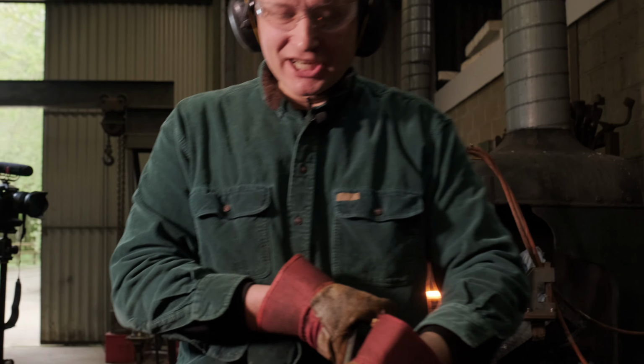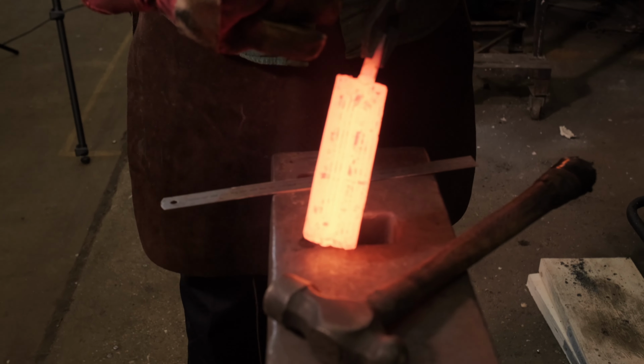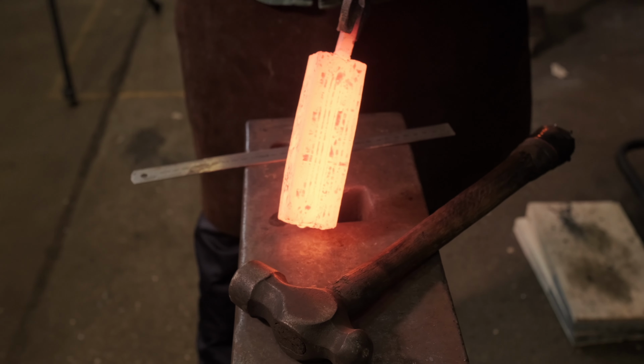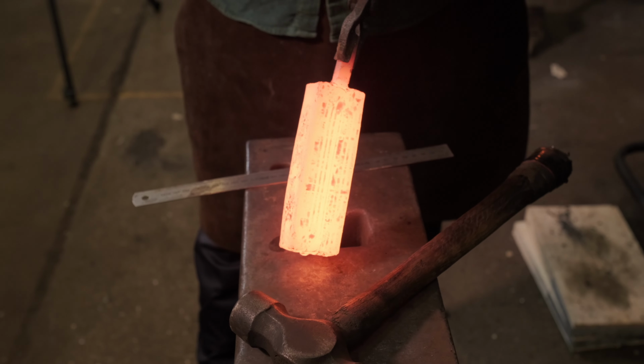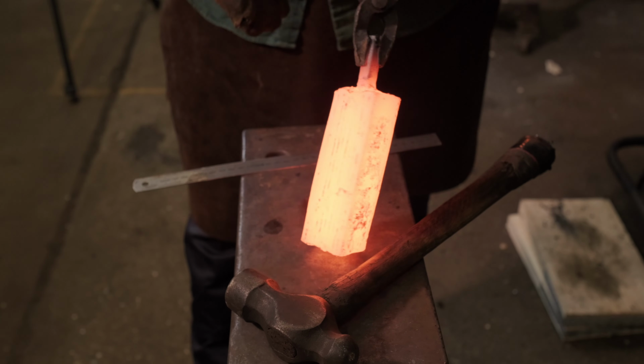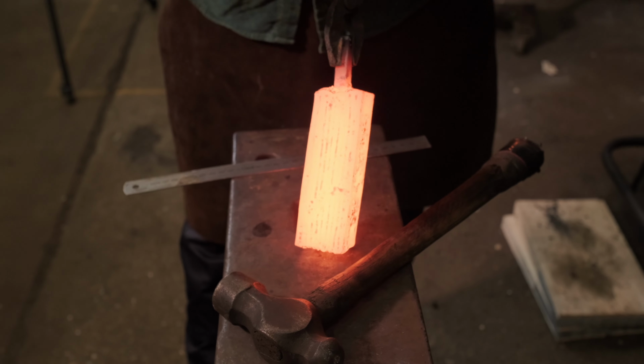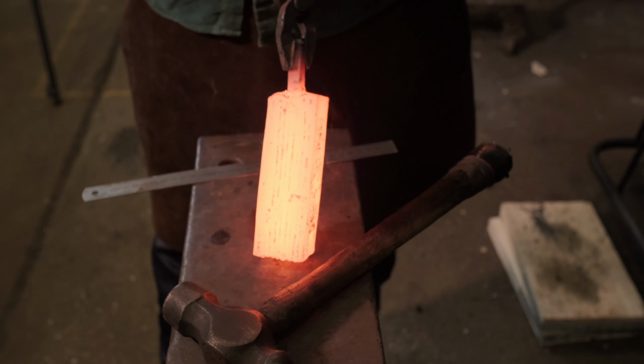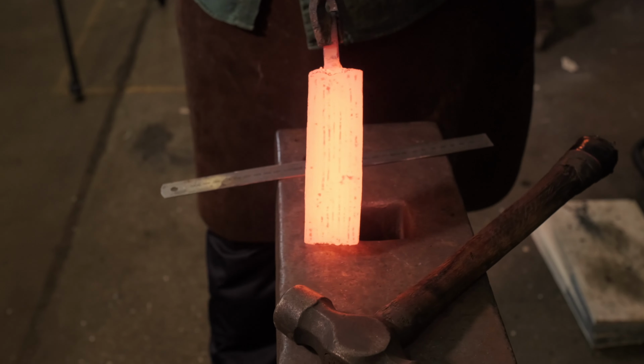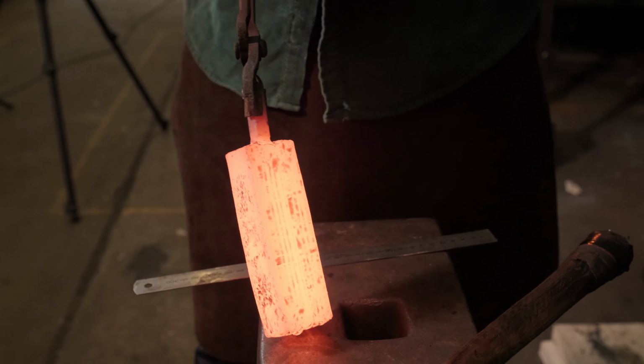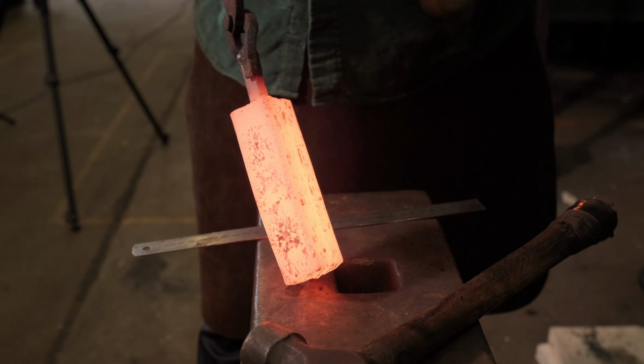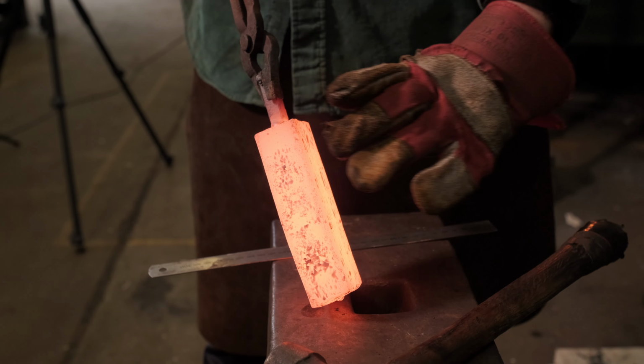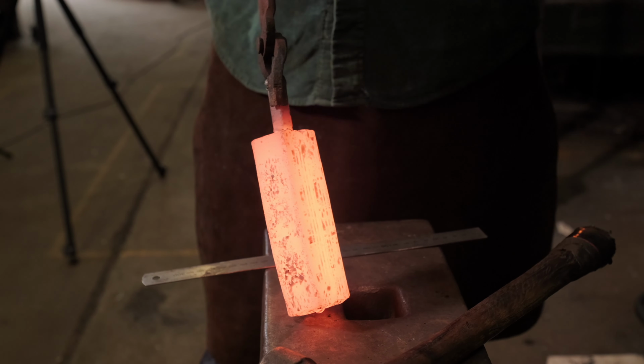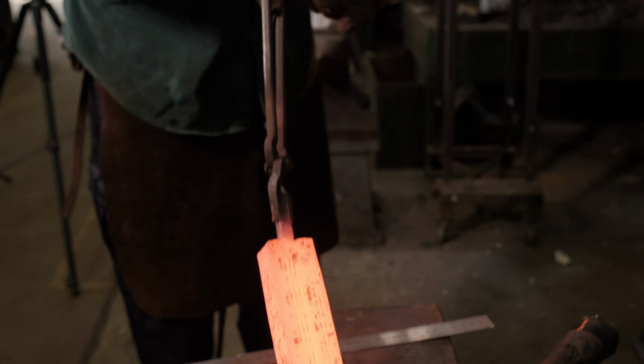So when you're forging this way, as you're drawing it out, temperature control is a must, because this is not how the steel likes to move. It might create splits, so you need to keep it nice and hot and keep a lookout for any splits. If there are any splits happening, just basically forge it back flat, and essentially you just need to keep an eye on it all the time.